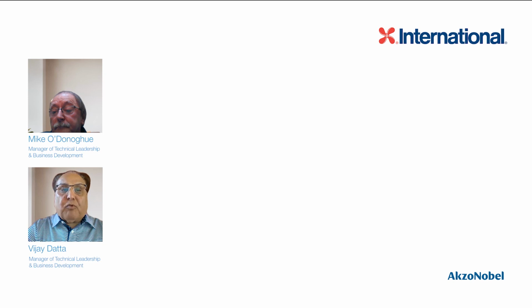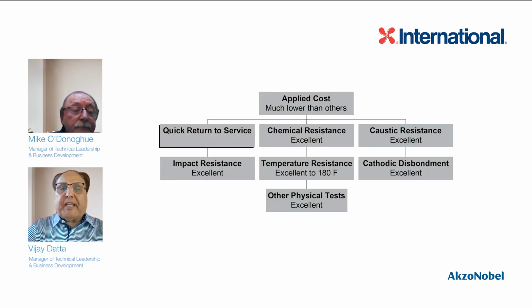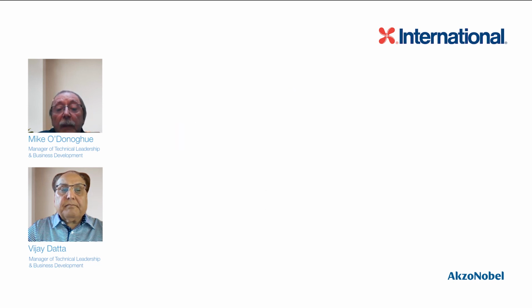Looking at the whole performance at a glance for Enviroline 376, it has a much lower applied cost because it's a single coat, excellent chemical resistance, and very quick return to service when you're in a bind. The impact resistance is really good, as we've got all the data for it. Temperature resistance, 180 Fahrenheit. The CD disbondment testing, excellent. And all these physical tests show a really good performance of this material, and hence we can get the 20 to 30-year lifetime from its good, effective use.